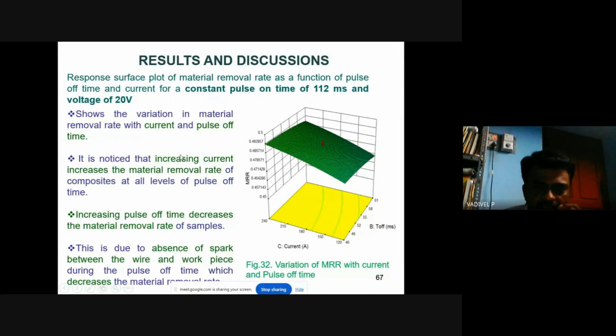Here the plot is between current and T off. Under these T off conditions, increasing the pulse off time decreases the metal removal rate. When the pulse is off, it decreases the metal removal rate. This is due to the absence of spark between the wire and the workpiece. So the spark influences the metal removal rate drastically.